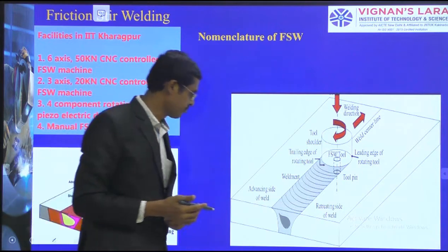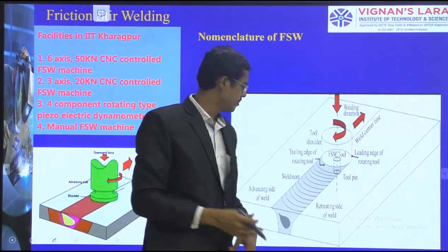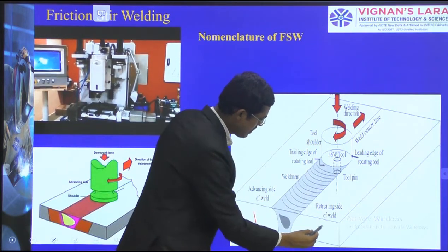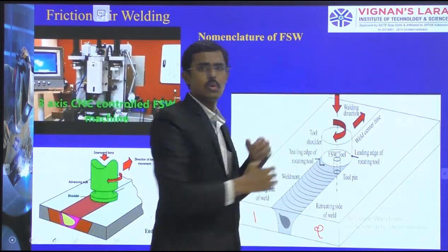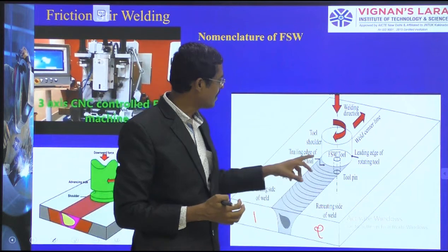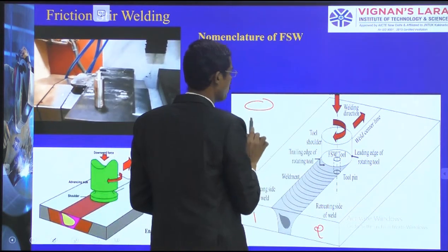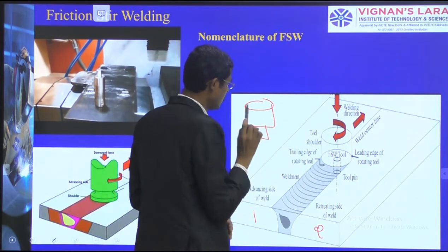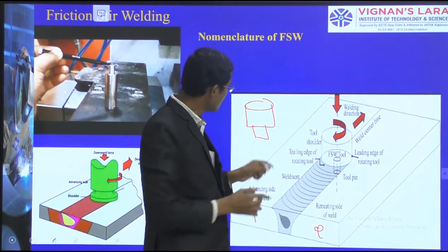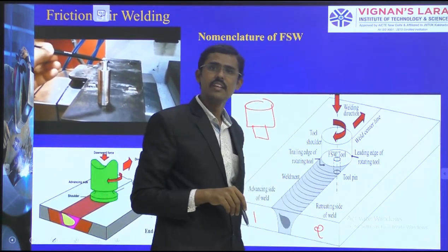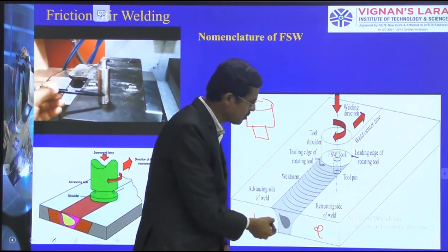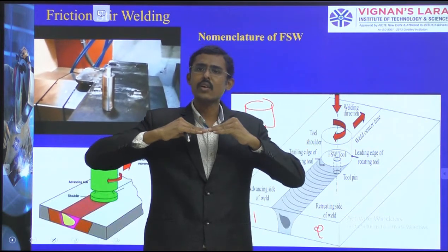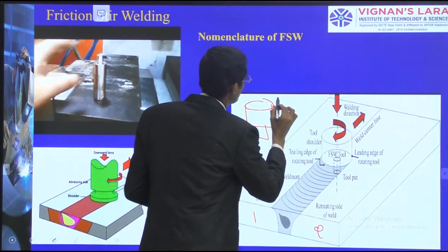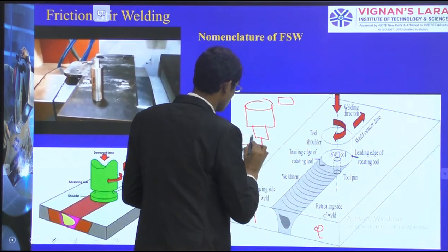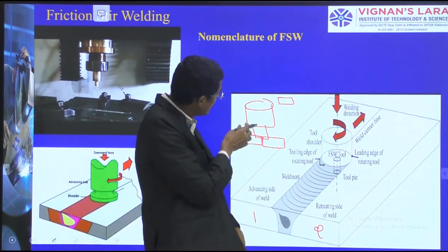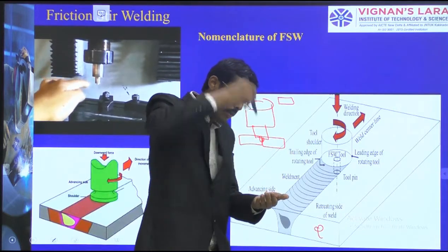So here is the setup. We want to weld 2 specimens, number 1 and number 2. How can I do it? I have taken one tool component which contains a shoulder and a small pin. This pin I am going to plunge inside the 2 specimens. There is no gap, 0 gap, and we have not done any edge preparation. I have taken 2 flat specimens and I am inserting this tool by plunging, putting a hole and going inside.